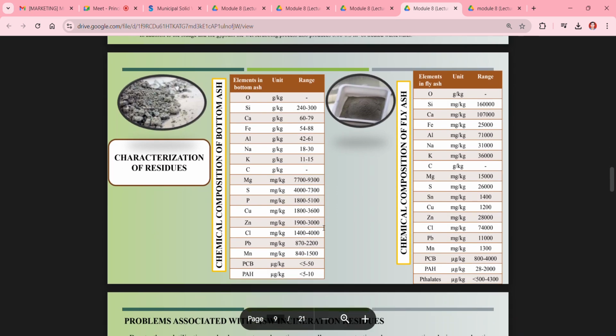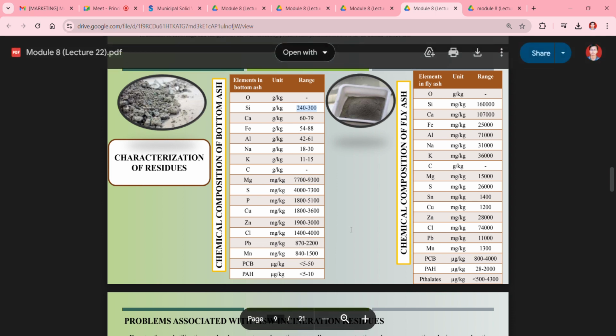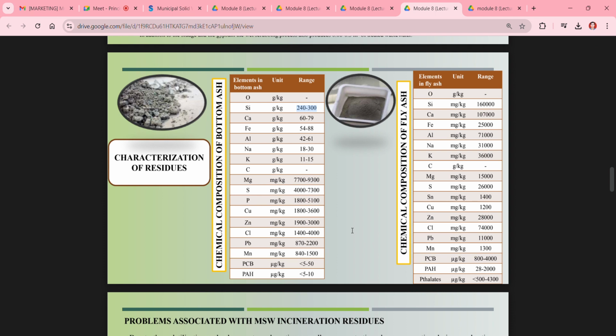Then if we are going to characterize this residue, it will mainly contain silica, calcium, iron and aluminium, with aluminium, Fe and calcium in a range of around 50 gram per kg, and the major amount is silica, around 240 to 300 gram per kg. There will also be some trace amounts of magnesium, sulfur, phosphorus and copper, depending on the chemical composition of the waste material which is going to be incinerated.